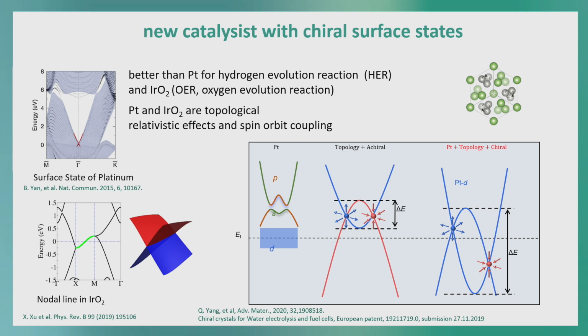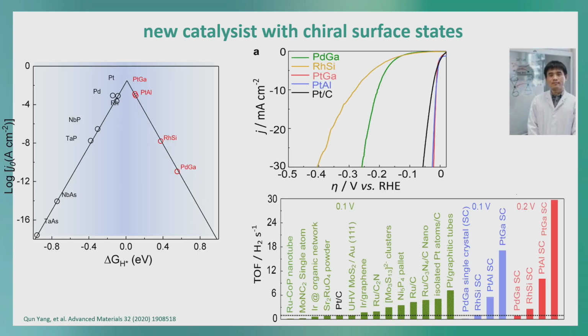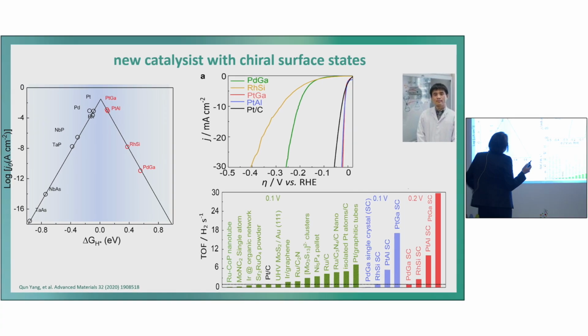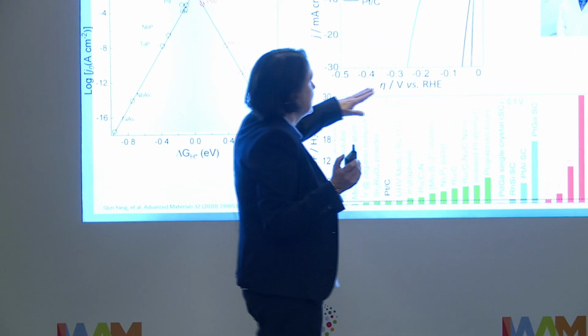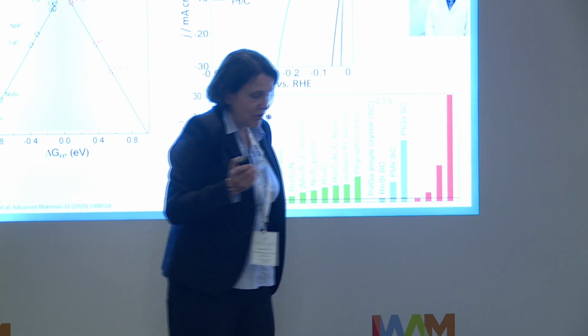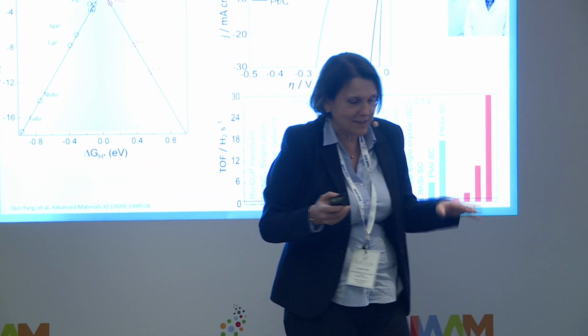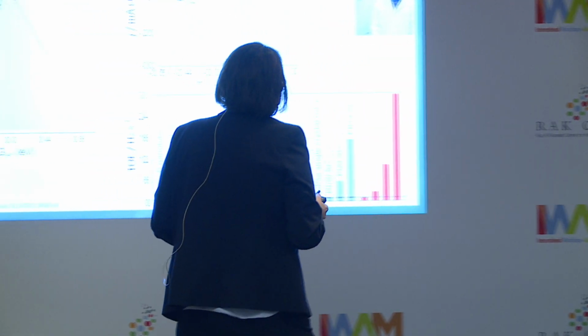Therefore, we thought if we look here at our chiral crystal, maybe it's better than platinum, because we have those Y points at two different energies, and we have a very wide energy range where we see interesting properties. And we were able to do electrochemistry, hydrogen evolution reactions. This everybody can do, I think. So we did the hydrogen evolution reaction, and this material shows quite good performance, even better than commercial platinum and so on. But it's still expensive in the sense that it's maybe not what we want.